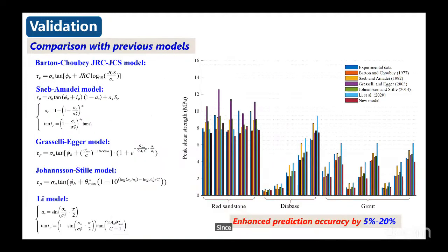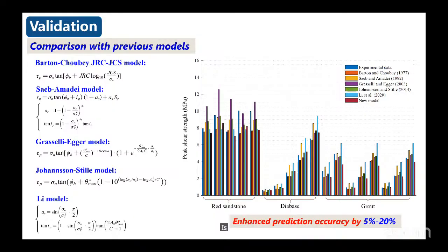We also compared the prediction performance of our model to a number of existing models, including the classic, very widely used Barton's JRC-JCS model, the Saeb-Amadei model, Grasselli's model, and the model I proposed earlier, which is a very simple prediction of the peak dilation angle. The comparison shows that overall the established model reached 5% to 20% enhancement of the prediction accuracy. It seems that it's not that much improvement, but our model is fully predictive, and some of the models listed here require co-fitting or additional direct shear tests.